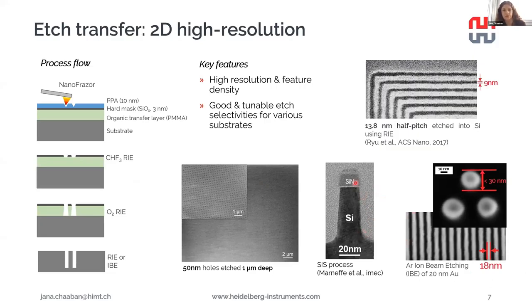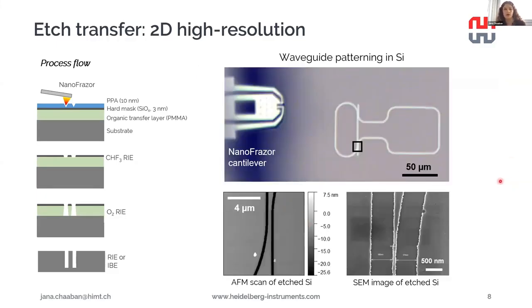So with this 2D high resolution etch, we can achieve very high resolution features. Here you see an example of patterns transferred onto silicon with 14 nanometer half pitch. It's also possible to transfer onto gold, and we can also achieve nice high aspect ratio features here. And also some repeated patterns of holes, also possible. And one example that we have been focusing on recently is also using the same high resolution transfer etch. We can create larger area silicon waveguides. So I show an example of this here.